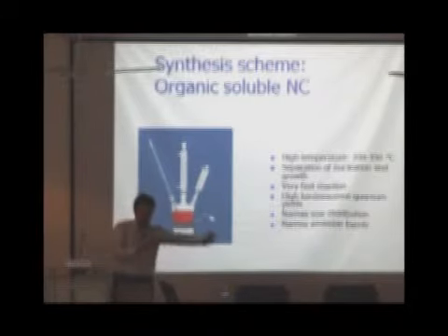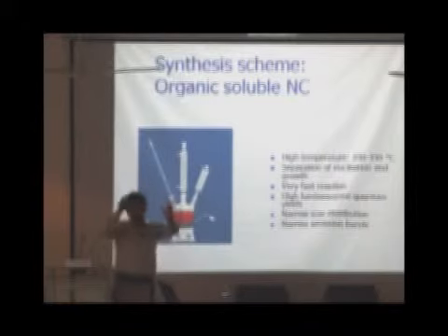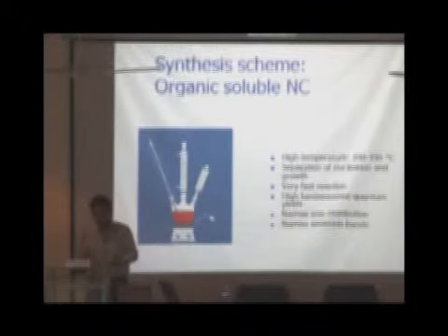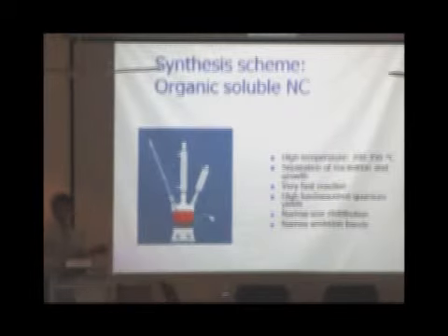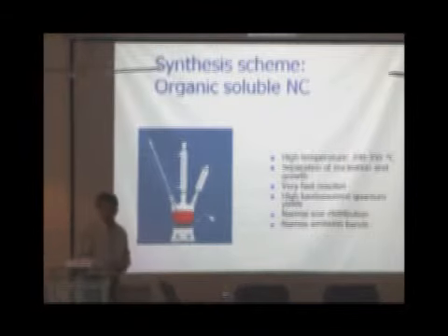So at one point you are making the nuclei and then just growing them over a certain period of time. If you kept making new nuclei at later times, you would get a spread of particle sizes. These kinds of high temperature methods ensure that you separate the nucleation and the growth, so you can get more monodispersed particles. I'll show you some transmission electron micrographs, and you can see that these are less than 5% size distribution.